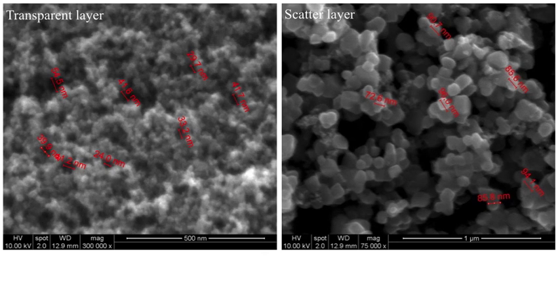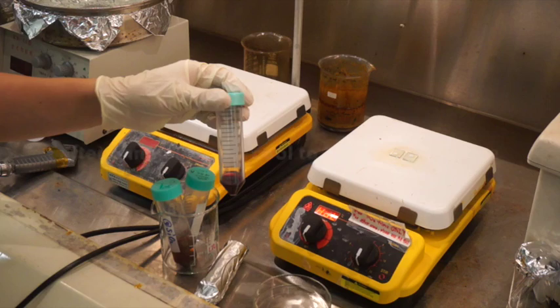While the samples are annealing, let's see the SEM image of the transparent layer and scatter layer. The transparent layer has a larger surface area to volume ratio so that it can be loaded with more dyes. And the network with 200 nanometers titanium dioxide, which is the scatter layer. This layer can scatter the light more effectively. Here shows the cross-section of 2 transparent layers. Each layer is about 3.5 micrometers.